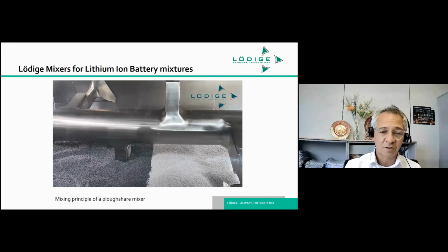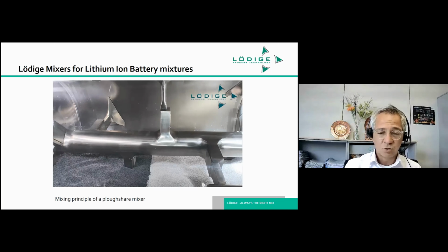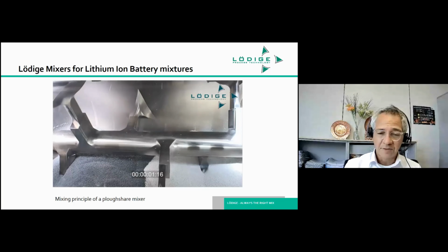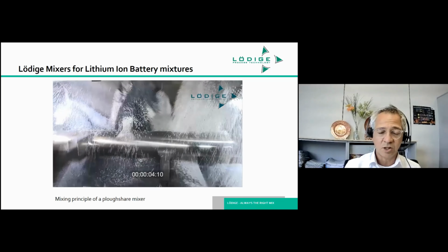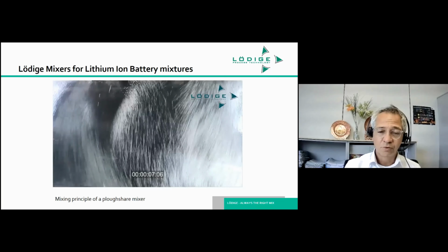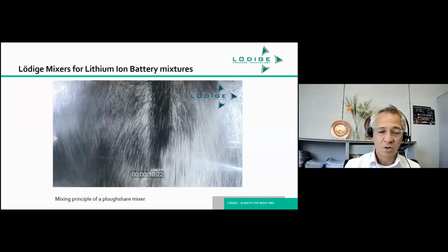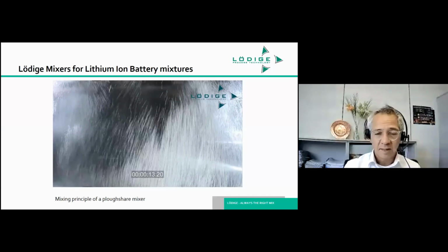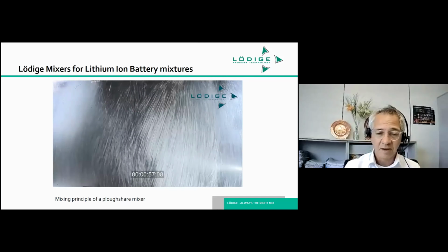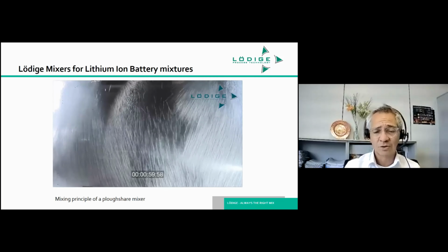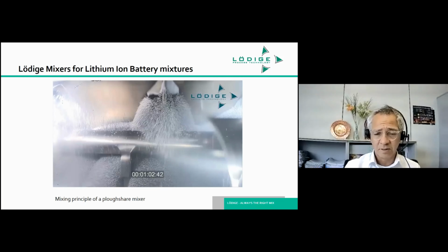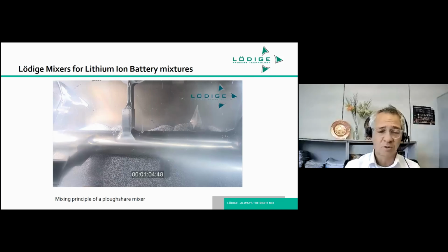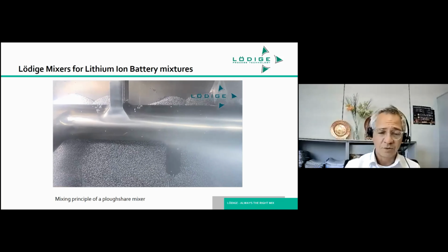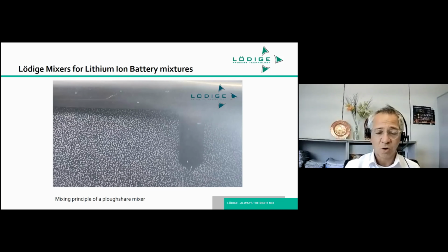And here's an example of how a Lödige mixer functions. It's a horizontal mixing shaft. On it are positioned the mixing tools. We have here a two-component system, black and white beads for simplicity. And this is where the mixing begins. By increasing speed, you get increased fluidization, you get three-dimensional particle movement, and thus interaction, interchange of the individual particles, creating a hopefully homogeneous mixture at the end. And after 1 minute of mixing time, we've cut it short here a bit, you will see that the composition is more or less, from an optical point of view, homogeneous. And that's the aim when using mixing equipment for battery masses or for any industry where you need to put components together.